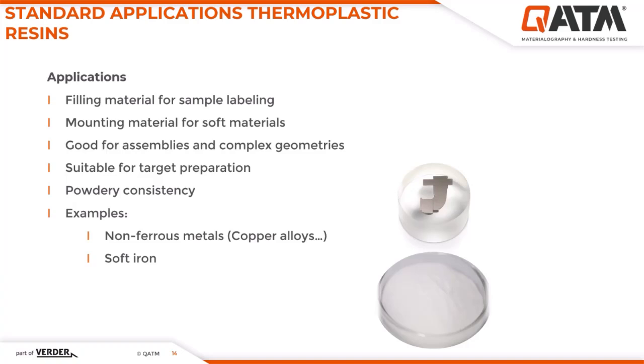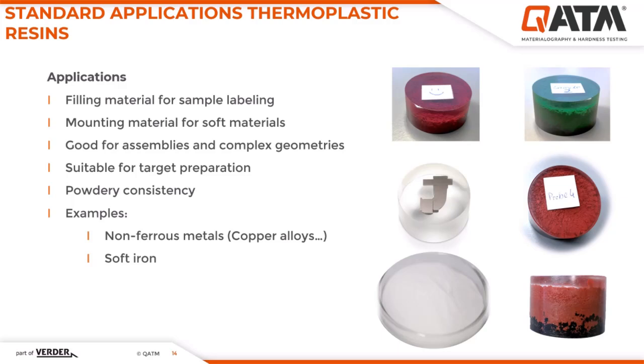Now let's turn to the thermoplastics. In hot mounting, their primary use is as a filler material for sample labeling. The sample is first mounted in an epoxy or a phenolic resin, then labeled with a tag, and finally covered with a small amount of thermoplastic. The high transparency of the thermoplastic is very suitable for this purpose.